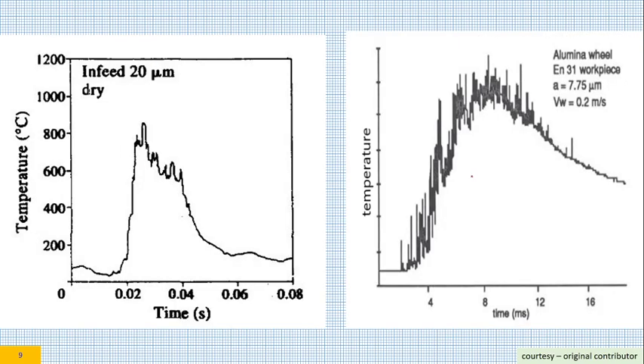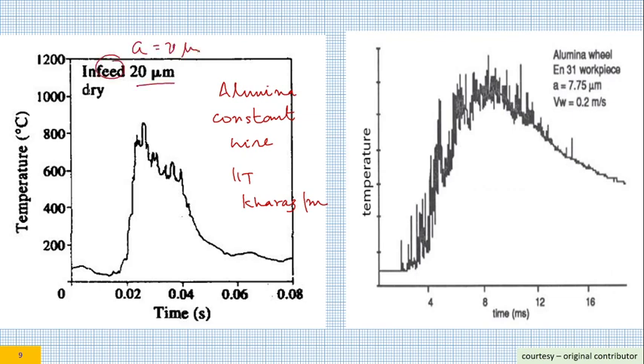So this was done using constantan wire at IIT Kharagpur, and this was done with an alumina wheel. This was at a down feed of 20 micron. This was dry. If you see here, this is EN31 steel. This is also an alumina wheel. The work material is also steel.